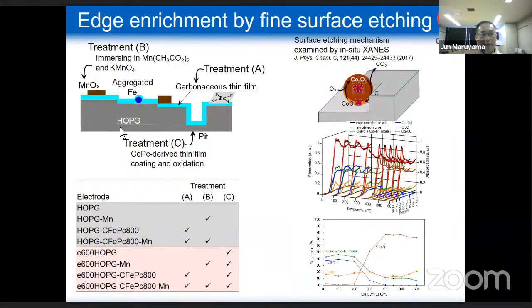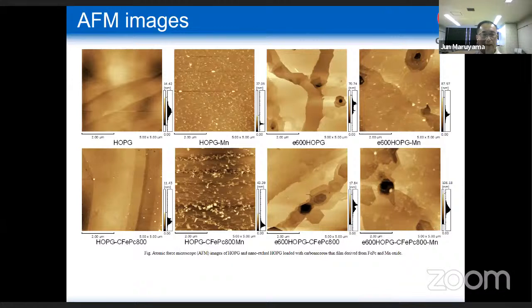And I use highly oriented pyrolytic graphite as a model carbon electrode. And I formed this active site on graphite. And I also loaded manganese oxide. And I also made a pit-like three-dimensional structure using the catalytic activity of cobalt oxide. These are the examined surfaces. I examined the various surfaces for oxygen evolution reaction and oxygen reduction reaction activities.